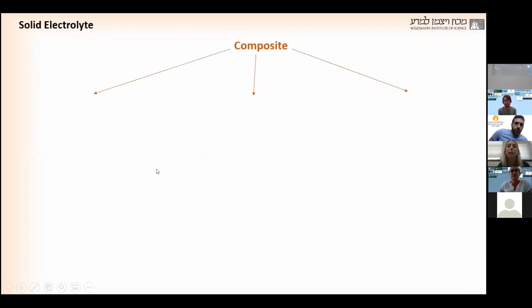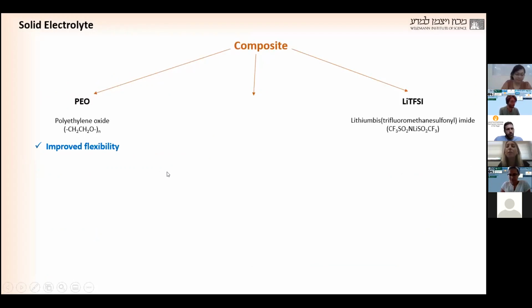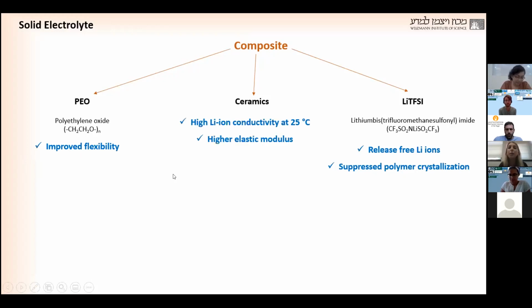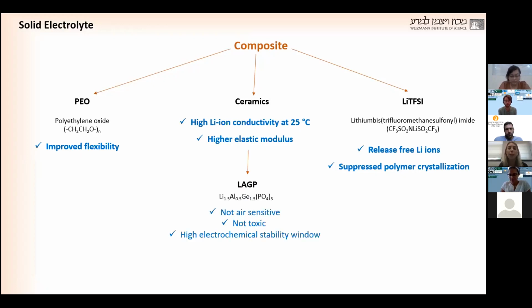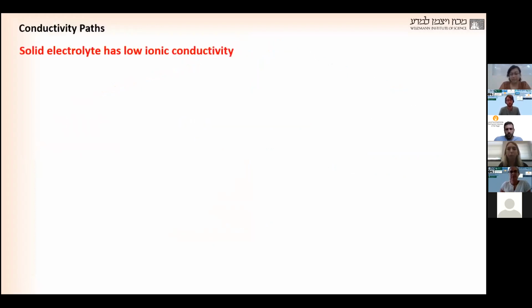The main solid electrolyte is a composite of the polymer PEO, to improve the flexibility of the battery; lithium TFSI salt, which releases free lithium ions and suppresses polymer crystallization; and inorganic ceramics, which have high lithium-ion conductivity at room temperature and a higher elastic modulus. In our system we use LAGP because it's not air sensitive, not toxic, and has a high electrochemical stability window. The problem with solid electrolyte is that it has low ionic conductivity.